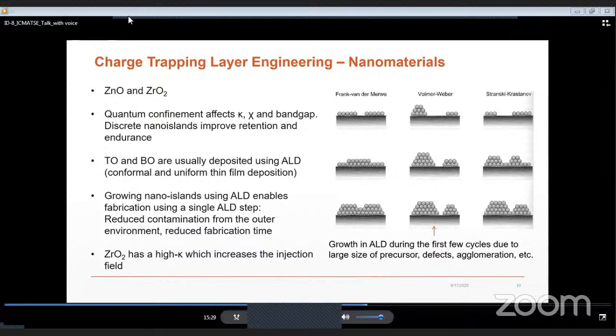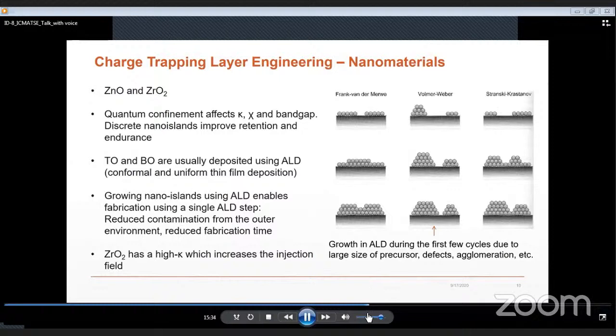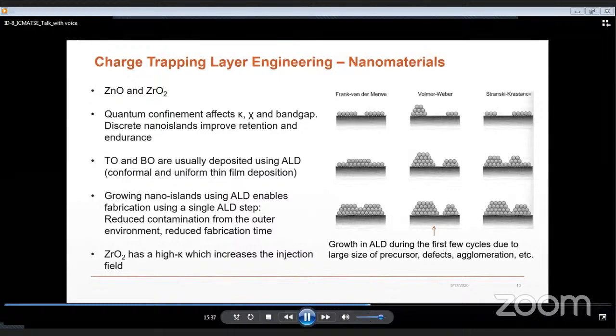Finally, the capability to grow nanomaterials using the ALD tool allows the conformal growth on structured devices such as FinFETs and gate-all-around FETs, as opposed to photolithography or even e-beam lithography of nanostructures, where the sidewall coverage would be difficult to achieve. So in the following, I have studied two materials, zinc oxide and zirconia, which I will be presenting in a bit. ALD is generally used to deposit ultra-thin, uniform and conformal thin films.